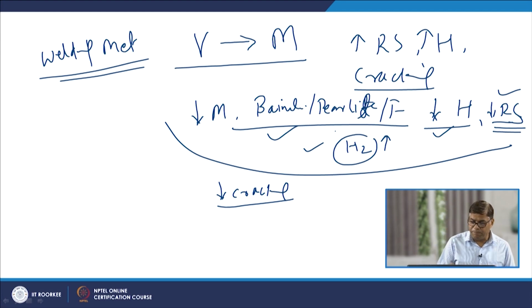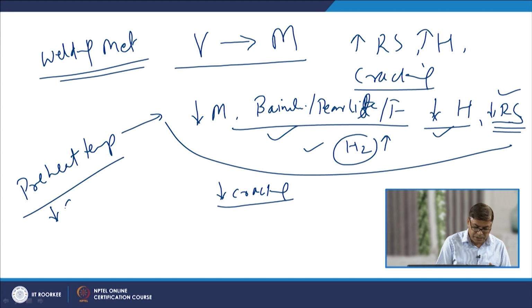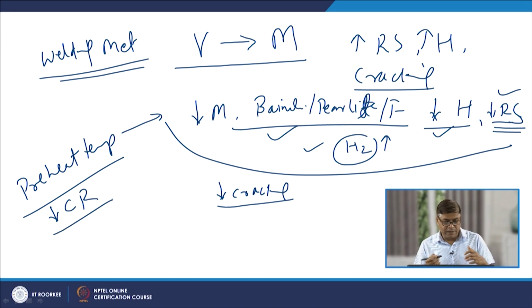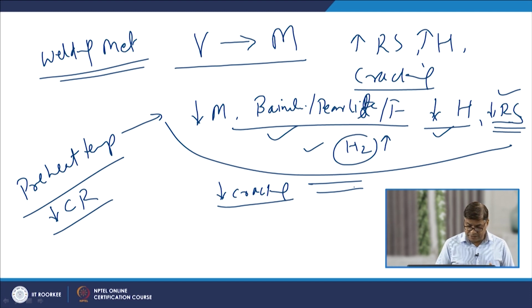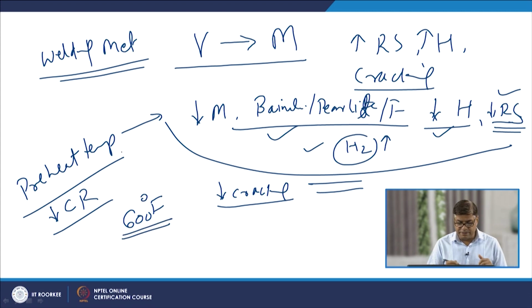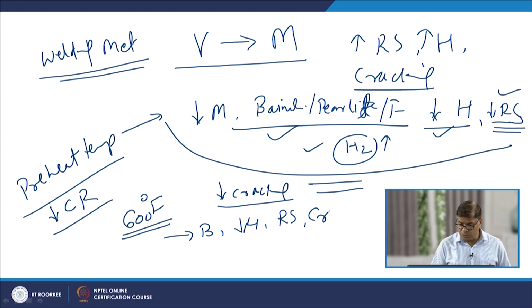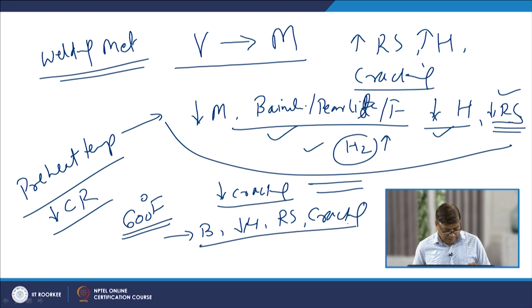There is one simple step for realizing this situation in heat treatable low alloy steel welding, which is the use of a suitable preheat temperature. We know that an increase in preheat temperature reduces the cooling rate experienced by the weld metal as well as the heat affected zone, so that these favorable conditions can be facilitated. It is very common that a 600 Fahrenheit preheat, if used during the welding of heat treatable low alloy steels, will promote the formation of bainite, reduce the hardness, and reduce the residual stress formation, and so these factors in combination will reduce the cracking tendency.